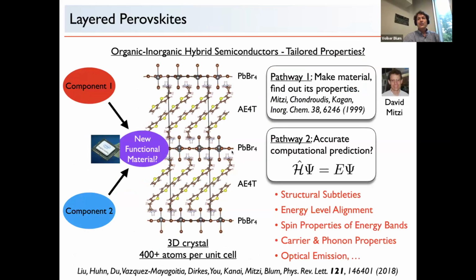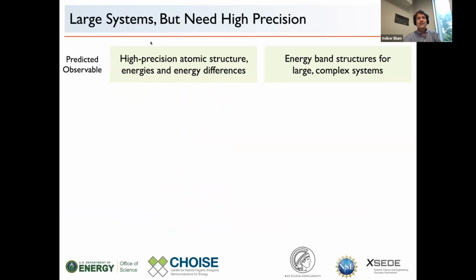I'm getting back to this slide, which you've already seen, for the layered perovskite. Given the starting point, I have about 8 minutes of the talk. And this just shows what we can do with a hybrid perovskite. As I said, these can be large systems, but they do need high precision because the bonding between the inorganic and the organic part, and also the bonding in the organic part, is quite subtle. And so our observables for this talk will mainly be high precision atomic structure, as well as total energies and energy differences, and then energy band structures that are calculated for large complex systems.